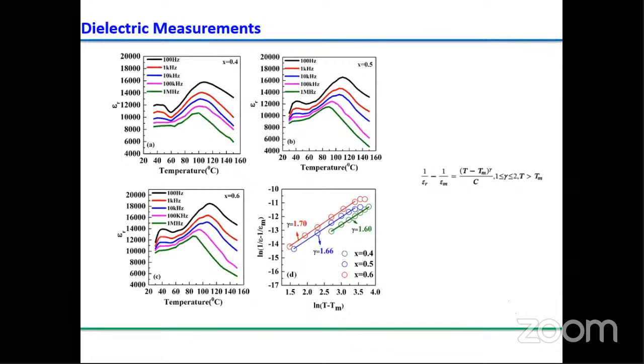One is around 40 and another one is at 100. Right. So that means these materials exhibited the two transitions: ferroelectric to ferroelectric, that means ferroelectric rhombohedral to ferroelectric tetragonal, and ferroelectric tetragonal to paraelectric cubic. So that is what we observed here.